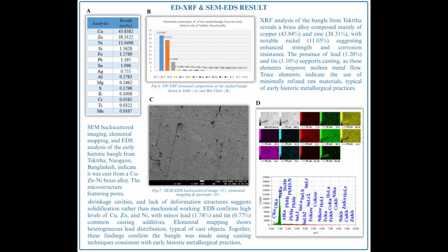Now, let's take a look at what the scientific analysis revealed. The EDXRF analysis showed that the bangle is primarily composed of copper and zinc, roughly 45% and 38% respectively, identifying it as a brass alloy. We also detected small amounts of nickel, iron, and other trace elements. The presence of nickel, though minor, may indicate intentional alloying to enhance the strength, hardness, and corrosion resistance of the brass, thereby improving the durability and overall quality of the bangle.